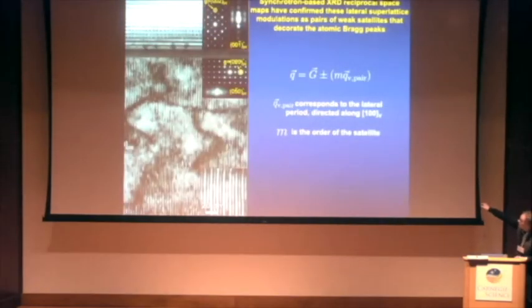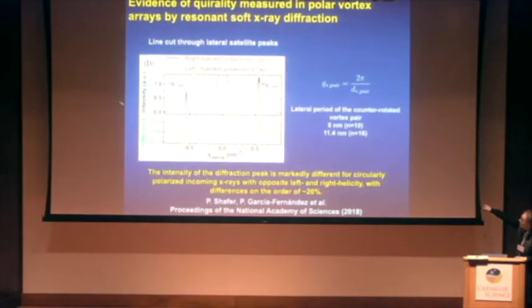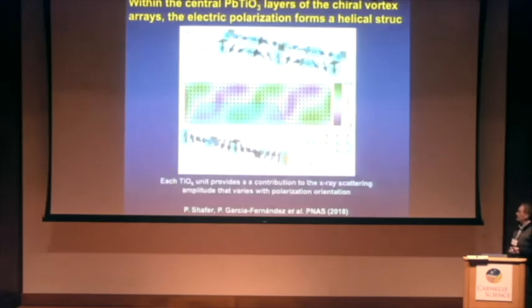If we perform a horizontal cut and plot the intensity of the diffracted X-rays, we can see two things. First, the appearance of the satellites with lateral periods that match very well with the counter-rotated vortex pairs. But second, that the intensity of the diffraction peaks is markedly different for circularly polarized incoming X-rays with opposite left and right-handed helicity, with differences that may be up to 20%. So this is a clear indication of X-ray circular dichroism, which is the fingerprint for chirality in the system.